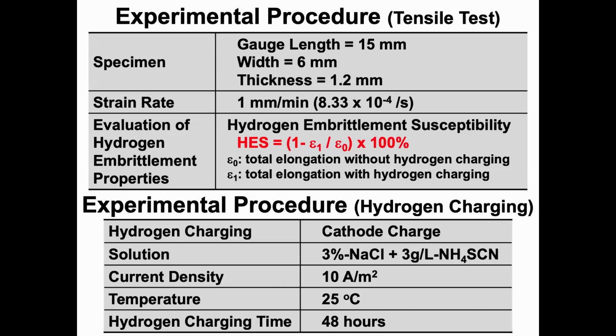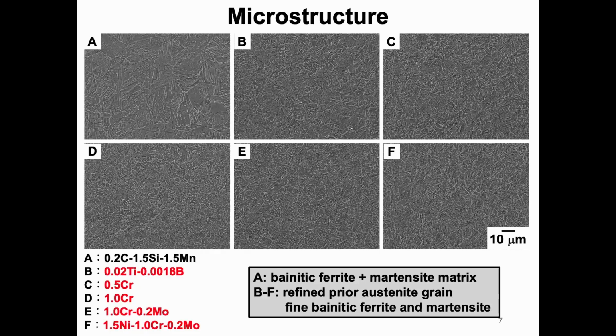The hydrogen charging was conducted by means of cathodic charging using a solution containing 3% sodium chloride and 3 gram per liter ammonium thiocyanate at a current density of 10 ampere per square meter at 25 degrees Celsius for 48 hours before the tensile test. Next, I'm going to show you the results.